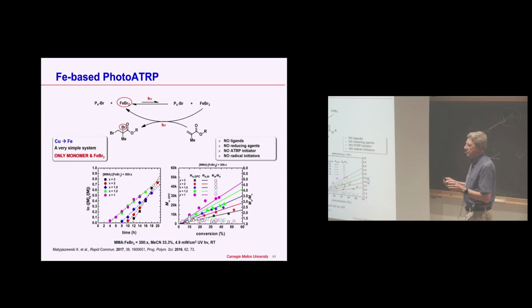This is in fact probably the simplest system you could think of, because normally we need a monomer, we need a catalyst, and we need an initiator. And here we work without initiator, because what happens here, this iron tribromide will react in the presence of light with methyl methacrylate and form this 1,2-dibromoadduct. So it would generate initiator in situ.